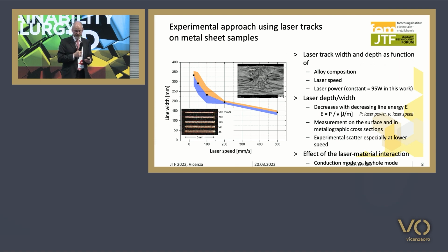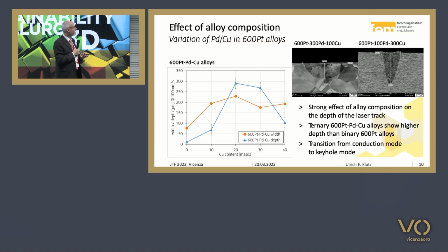I will show you an example of how this looks exactly. Here we see a very small laser track with low depth. The scale is 40 microns, so this is a typical example for the conduction mode. This is done in a 600 platinum alloy with palladium and copper.